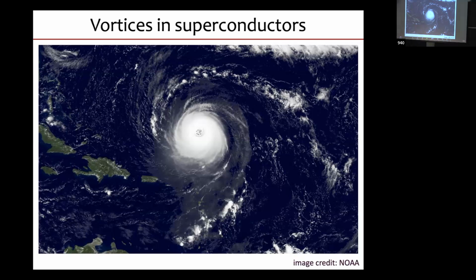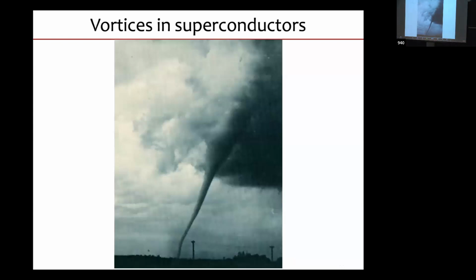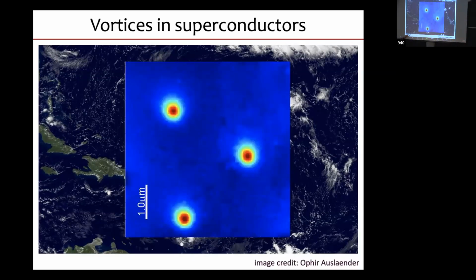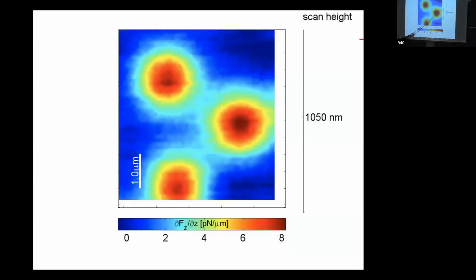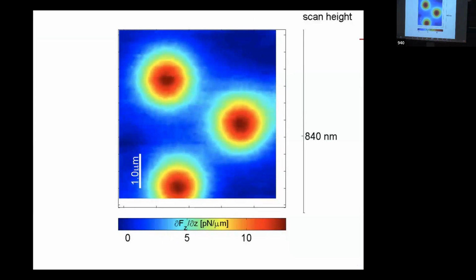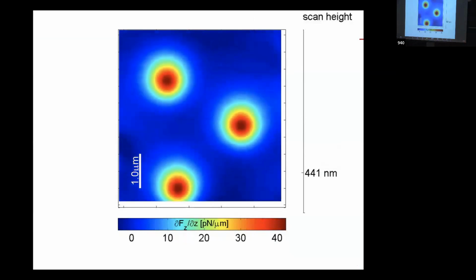And magnetic fields aren't like that. So if this were a whirlpool of superconducting electrons, it would be creating a magnetic field, which you could use to see it. But the magnetic field would spread out quite quickly as you leave the material, and that makes it harder to see. But if you go sufficiently close to the surface, it might look like this. That's actual data. But if you back up from the surface, so this is an image of those three vortices where we're scanning a micron above the surface, this is actually a scan with a magnetic force microscope. And what you see is they look pretty blobby. And if we went to 2 microns, you wouldn't even see them because they would be completely spread out. So you really have to go quite close to the surface of the sample in order to get a pretty good image of the vortices.